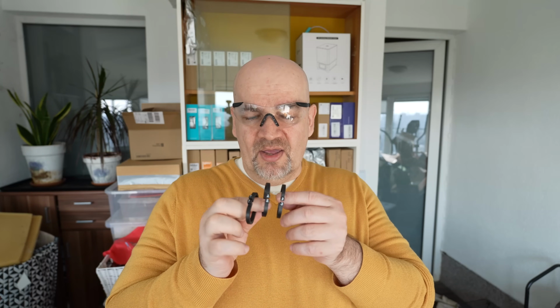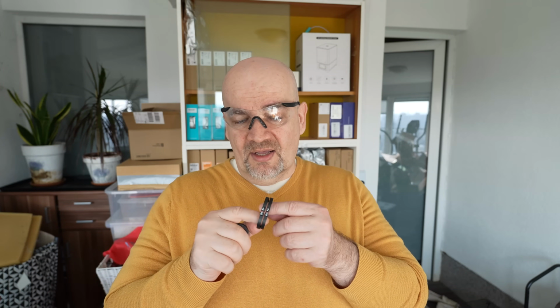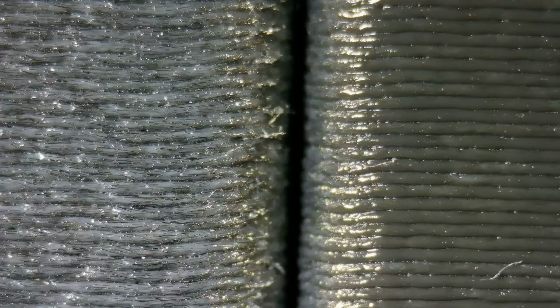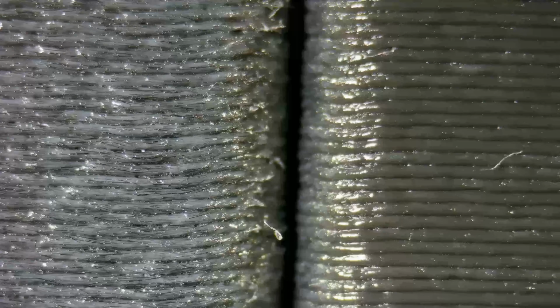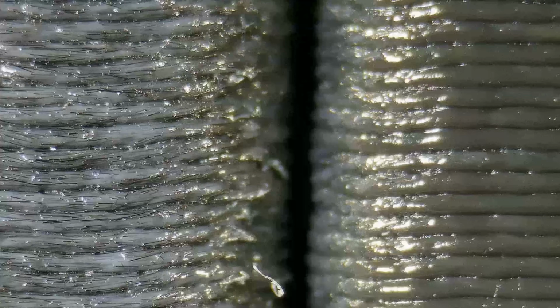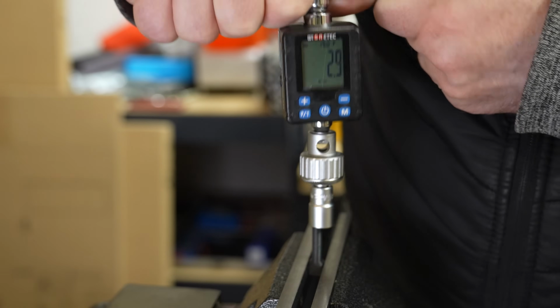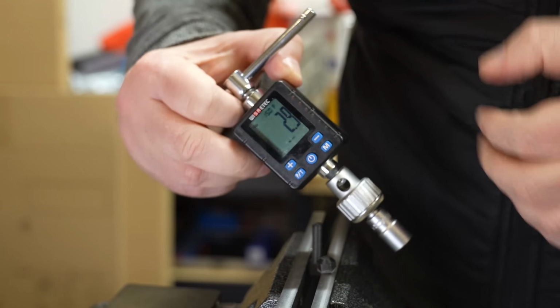These two carbon fiber reinforced versions have great mechanical properties. I really like these materials. And the question of whether the core works: yes, we will have less wearing of the nozzle, the fibers are not exposed on the surface, and also we will improve the layer adhesion. And this can be seen not only in the layer adhesion test, but also in the shear and the twist test where I have those vertically printed test objects.